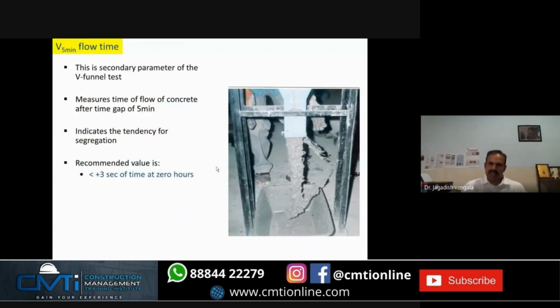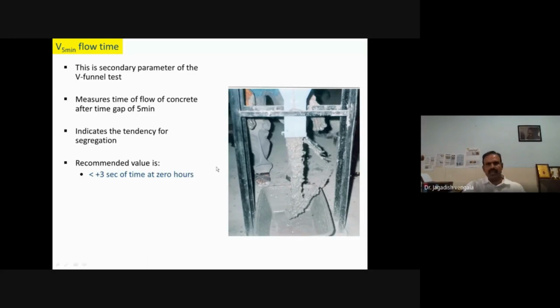Next measure using the same V-funnel, we call it as a V-flow time for after 5 minutes. What does that mean? You will place the concrete, you will measure the time taken to flow through V-funnel. That is the 0 minutes immediately after placing the concrete. This is in the second case, what you do, you place the concrete, you fill the V-funnel with the concrete,